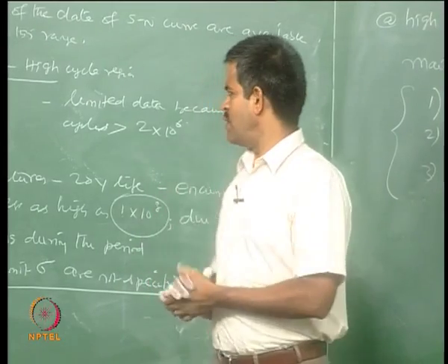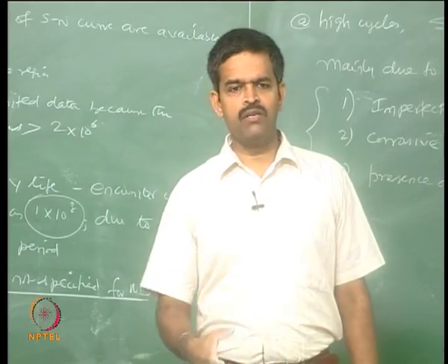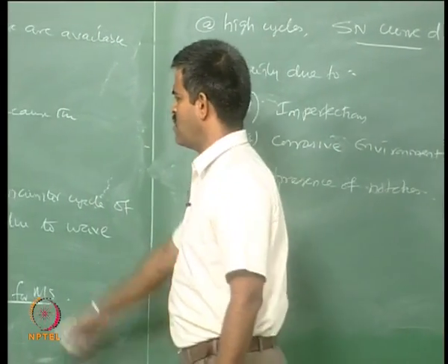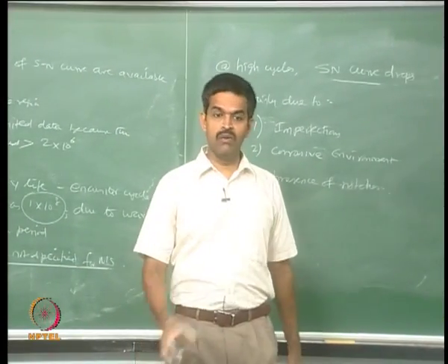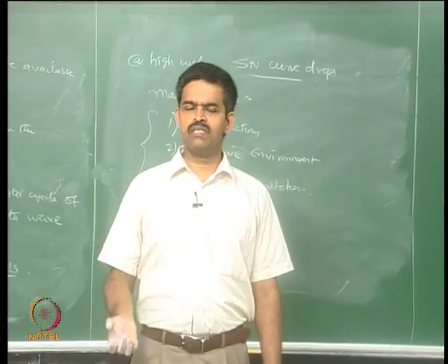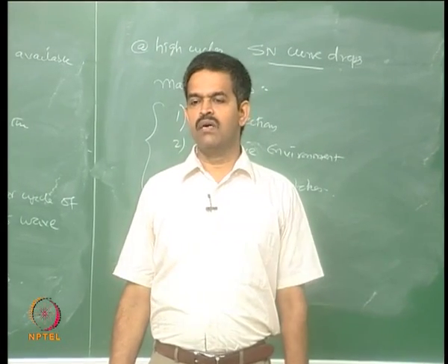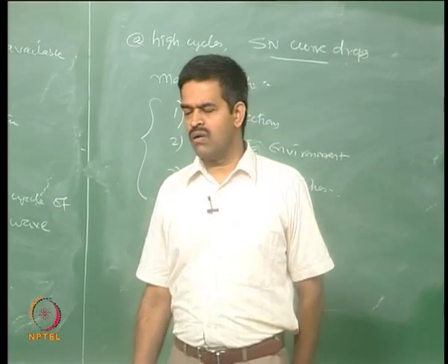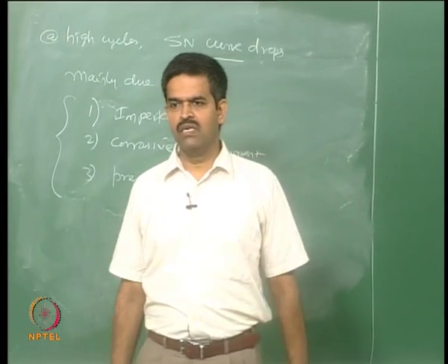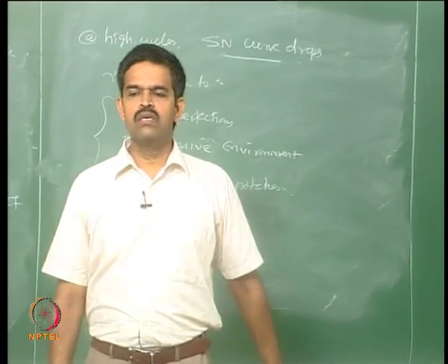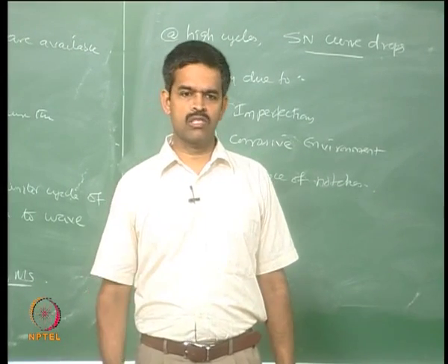But when you look at the high cycle and low stress ranges which are applied to marine structures, you will see that the marine structures in the given design service life see about 10^8 cycles, for which the SN curve family is limited. Okay. So, the fatigue life prediction based on SN curves available in the AWS or other equivalent curves is not sufficient to accurately predict the fatigue life or the fatigue damage, whether you use narrow band or broad band or time series calculation using the rain flow counting method. So, with this we conclude all the 4 module lectures of advanced marine structures.